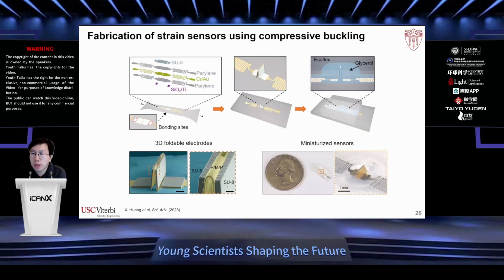And the way we fabricated this is to use a mechanically guided assembly process. Basically, we pattern each layer using planar microfabrication, and then we attach them to a pre-stretched substrate. Upon buckling, we can form this origami-inspired triangular shape, as you can see here.